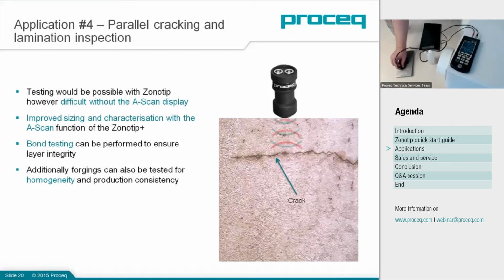Let's see if I can find that again. There we go. It's over there. So that means we've got a delamination 3 millimeters away from the back wall surface. And you can use the A-scan, we don't have so much time here, to really characterise and size that defect if you bring the gain down, for example.